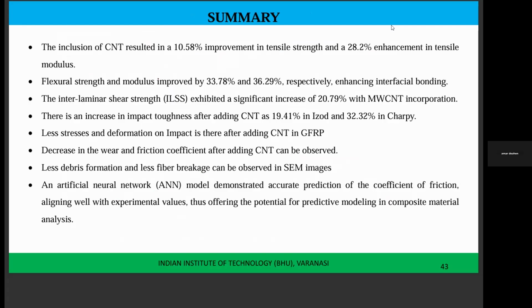Also you can see there is an increase in impact energy, both from the Izod as well as the Charpy test. In the case of the coated one, you can observe less debris and less fiber breakage, because you are getting the increased strength. That means there is some kind of bonding at the lower level, so you can expect very little breakage.